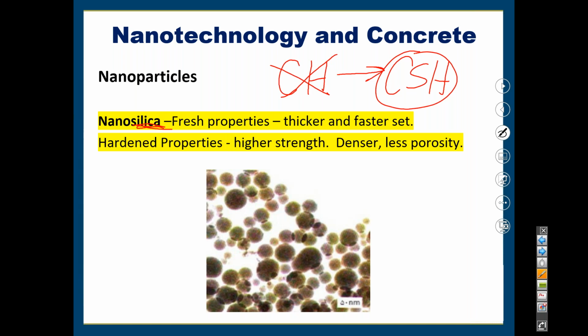And then the third thing that it does is it has a pozzolanic effect and has a filler effect by itself. So this is what I meant. This is the pozzolanic effect that we have up here, where it reacts with the CH to create more CSH, but it also acts as a filler where it just ends up filling additional space in the concrete. So it behaves as a nanofiller between the gel products of calcium silicate hydrate,